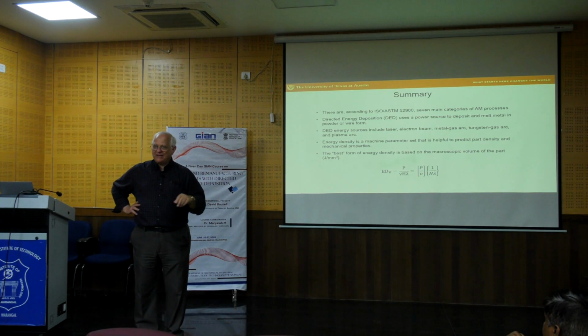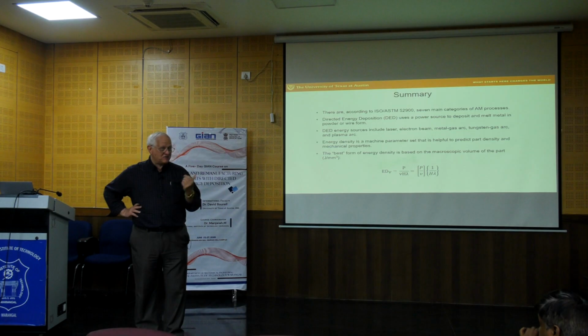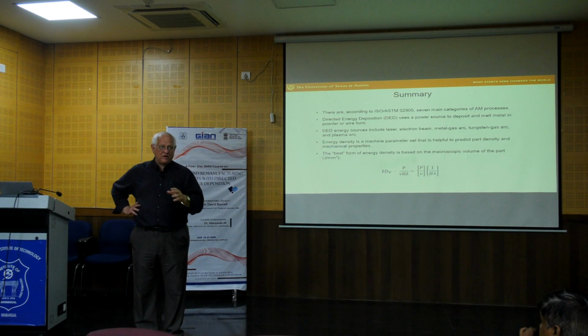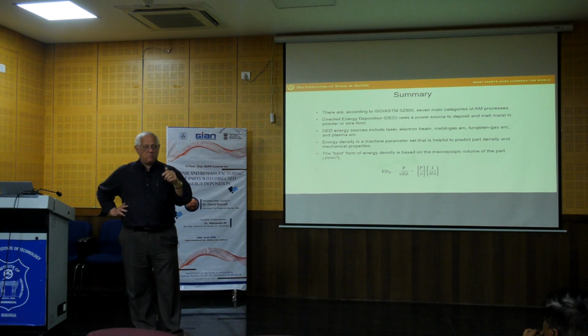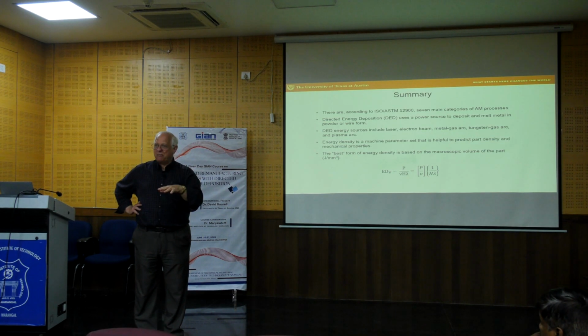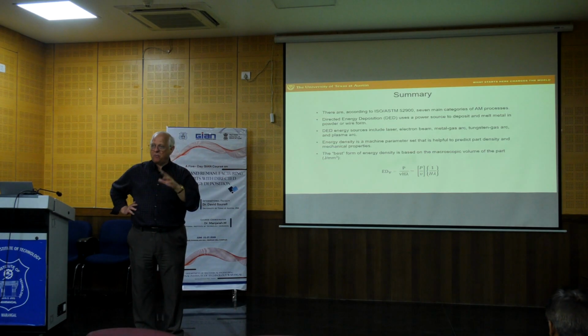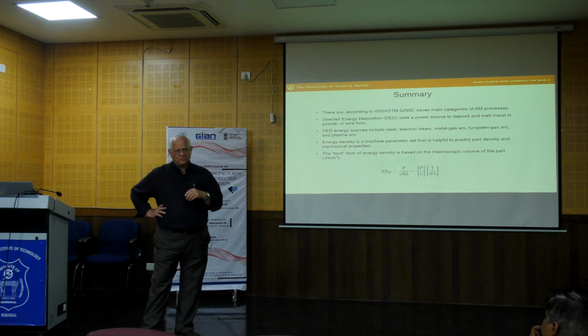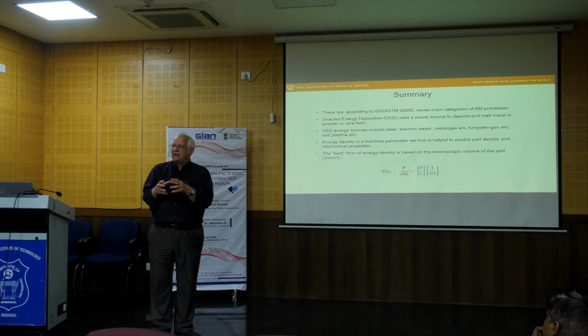The other half is they stole from my friend Behrokh Khoshnevis at the University of Southern California, who had a technology out in the early days called selective inhibition sintering, where instead of putting down a coupling agent, he would put down a decoupling agent and then blast the part with light or energy on a surface basis, and where the part was, the part would bind together, but where the decoupling agent was, the part would not bind. So multi-jet fusion is really a combination of these two.